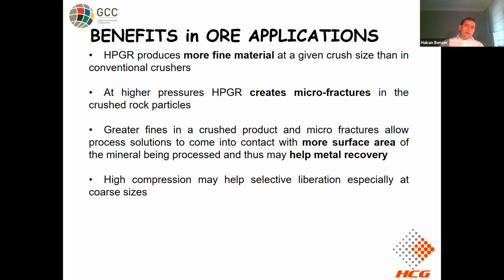The other part is, again, in some cases, depending on the mineralogical conditions of the ore bodies, we can see increased metal recovery. For instance, in one case, we measured two lines. One is running with HPGR and the other one is running with the conventional crushing system, which is feeding the heap leaching operation. And we observed 6% more recovery with the compressed bed system application. But you need to manage the fines produced through that system. This is an extra cost, but it has to be managed. Once it's managed, the metal recovery stays there.